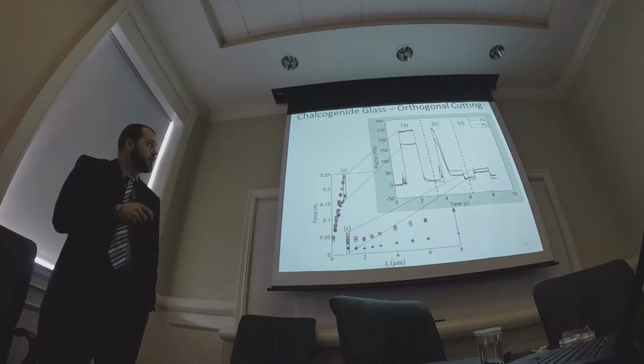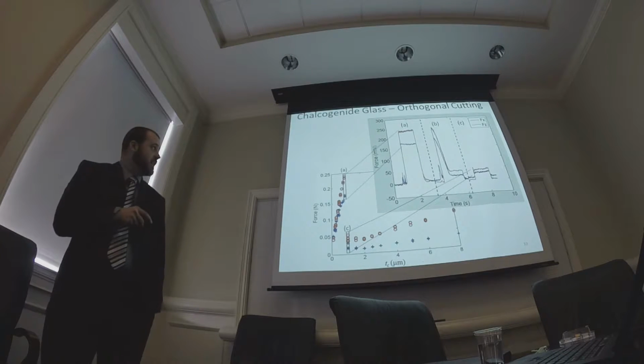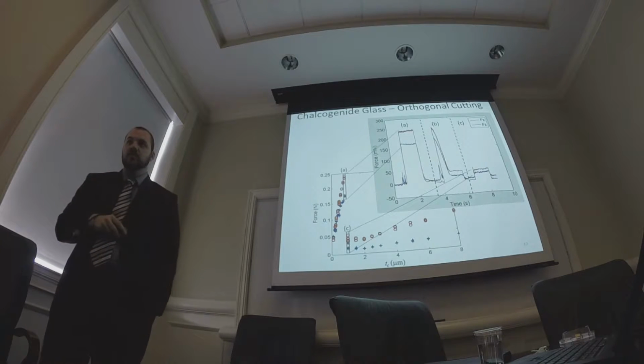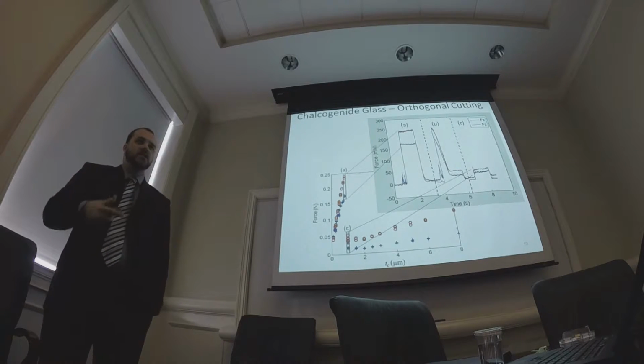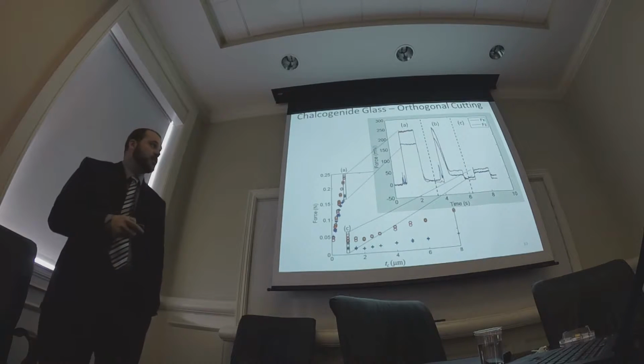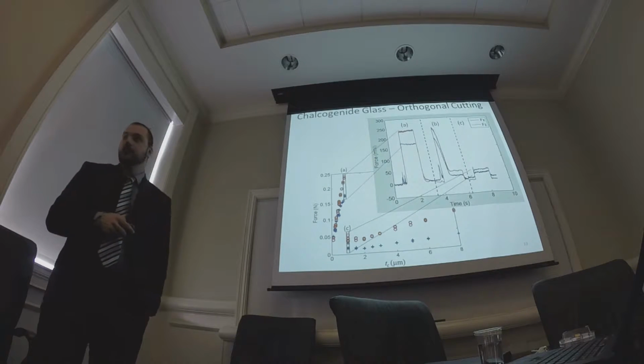But if we look from the last test here and the next test cutting at this parameter, we see a force that we would expect if we followed along this trend initially, and then a drop to what we then see continuing through here. This is what we believe is the ductile dominated state, and then as fracture begins to occur, it propagates, and then this is the state at which the brittle fracture has reached the most fracture that it's going to get, and it just stays at that level.